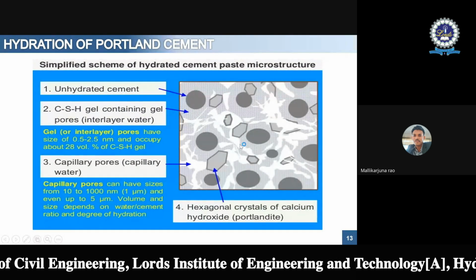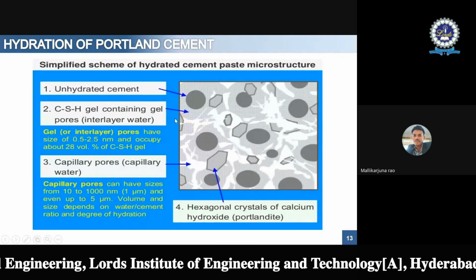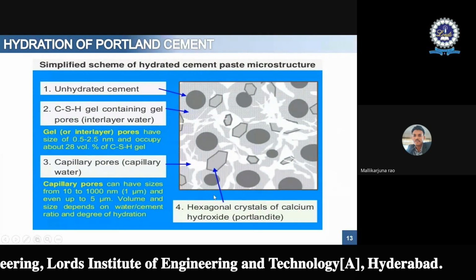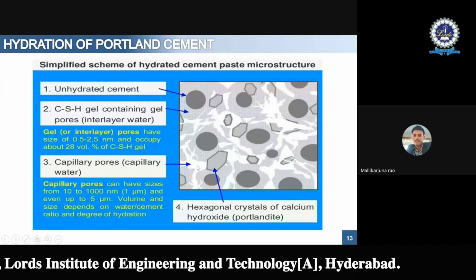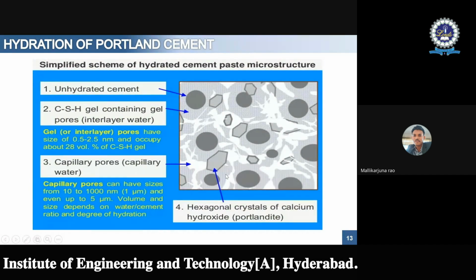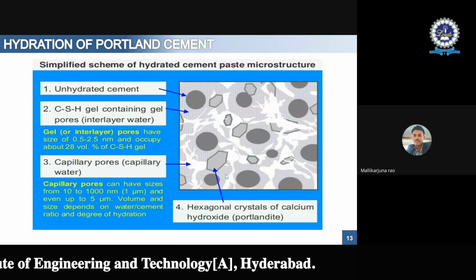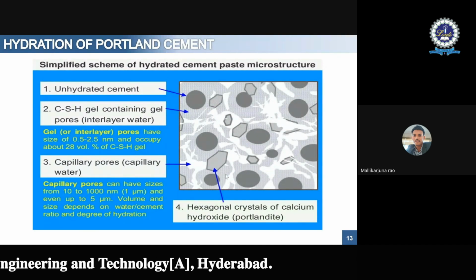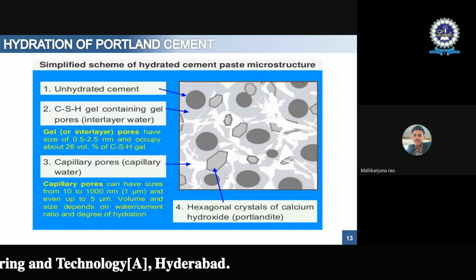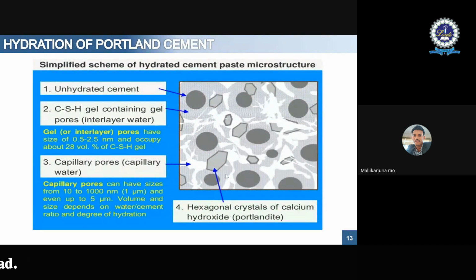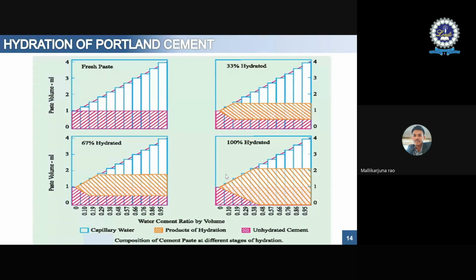See here in this picture, you can see some of the unreacted particles that are left out, and some of the capillary pores are there, where hexagonal crystals, portlandite, which is calcium hydroxide, are present. It does not contribute to the strength, but we have to reduce that calcium hydroxide through our materials, which are nothing but fly ash, GGBS, rice husk ash, metakaolin. Those are going to react with that calcium hydroxide, and additional CSH gel formation would be there, and it is going to contribute a good amount of strength.